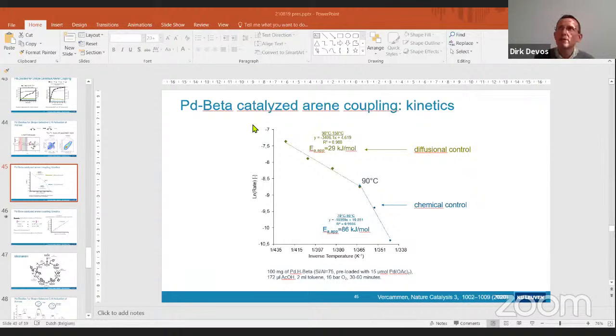That's also the risk if you go for pore engineering, and you try to create mesopores and whatever, but then you also lose your shape selective environment. And if you end up with palladium sitting in a meso rather than in a micropore, out goes the selectivity. So yeah, I hope that's a bit clear. What you can also do, of course, is play with the size of the crystals, and beta, luckily, is one of the systems that typically comes in small crystals. So you have 100 nanometer crystals in an industrial beta.